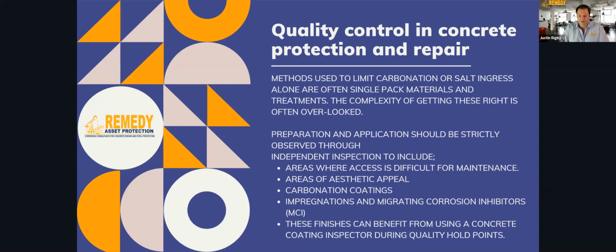Same as your migrating corrosion inhibitors, and silane treatments. Five minutes after you apply that stuff, you can't tell it was put on. The concrete looks the same as what it did before. So the only way you can really prove that it was done properly is that it's documented. Somebody's there to witness it being applied. They're reporting that the surface was prepared properly to accept the treatment, as well as the volume and the spread of the material.